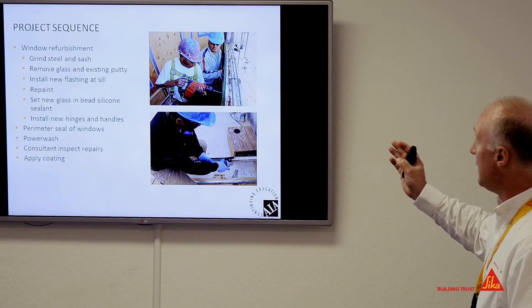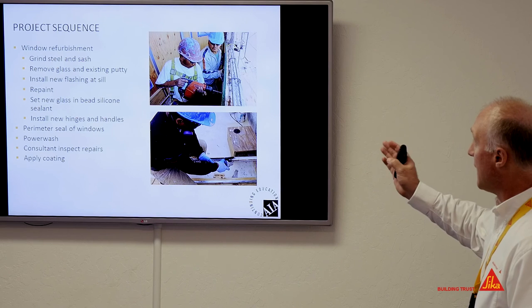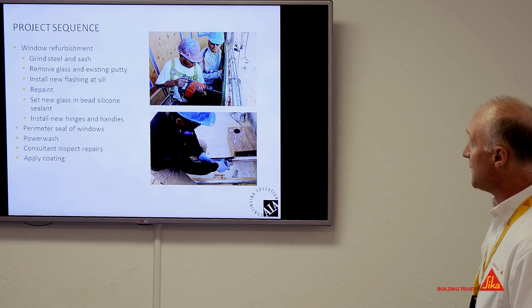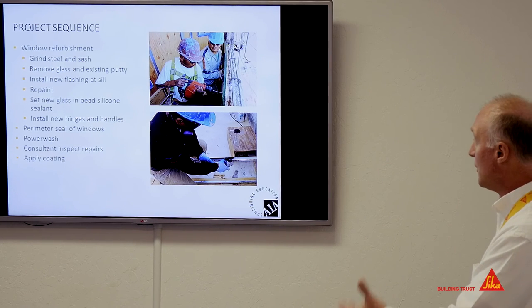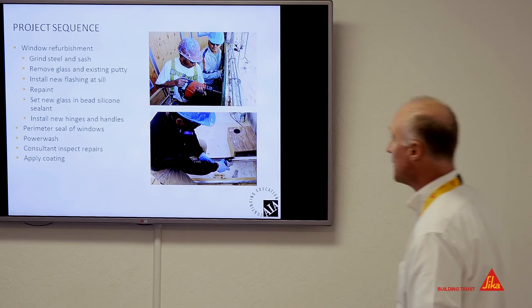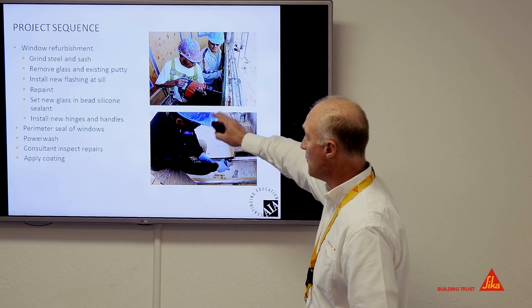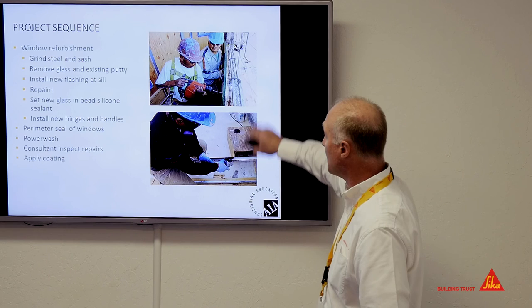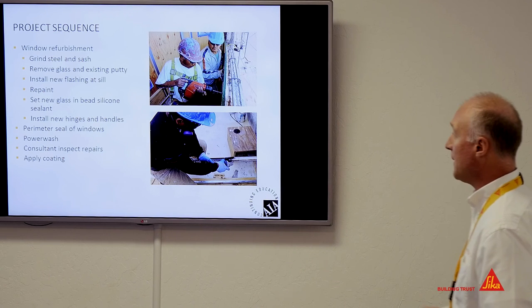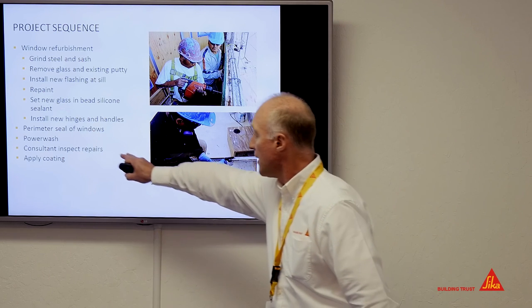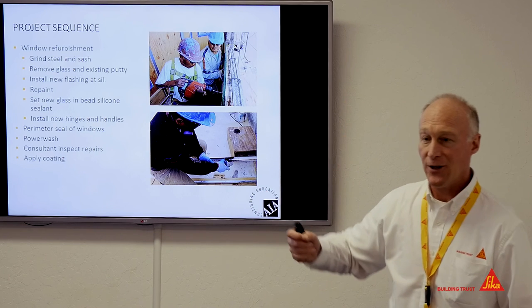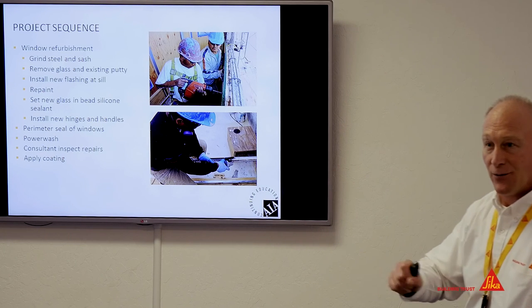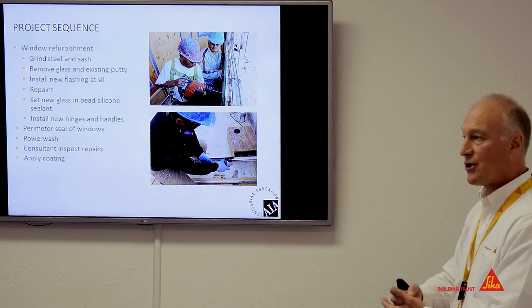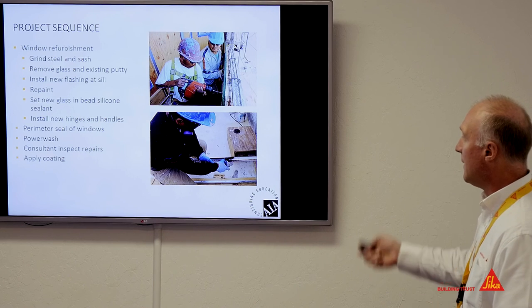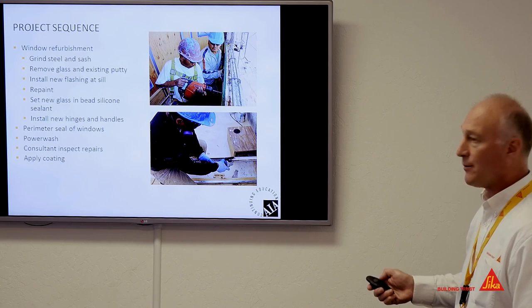And here they were grinding the sashes, removing the glass, installing new flashings at the sills, repainting, new glazing, new glass, bead of silicone sealant, new handles, perimeter seals. So all of this stuff taking place around the windows. But after the repairs were done, the consultant would go back up there, use like a Schmidt hammer to test for compaction and quality. And then after that was done, they applied the coating.